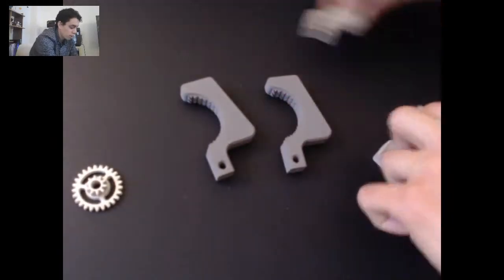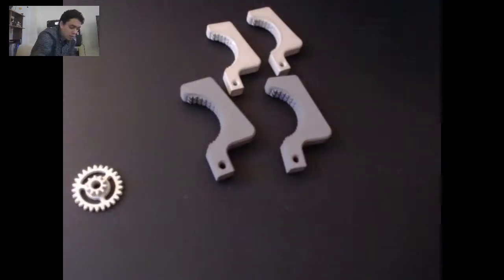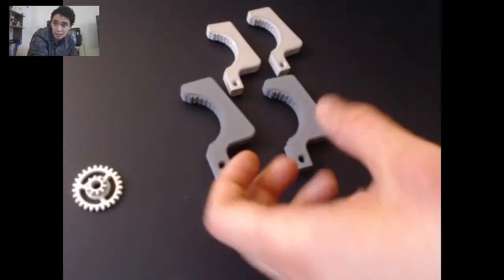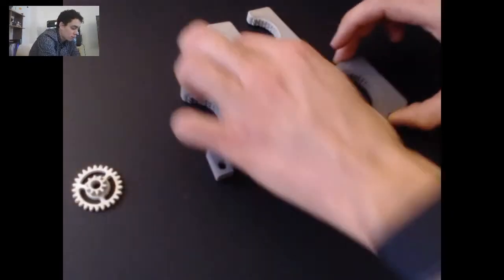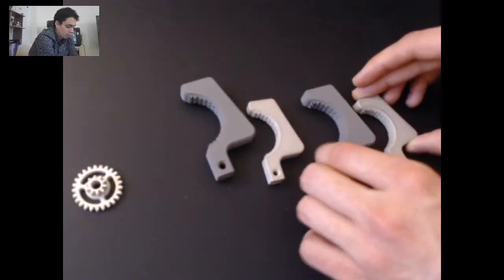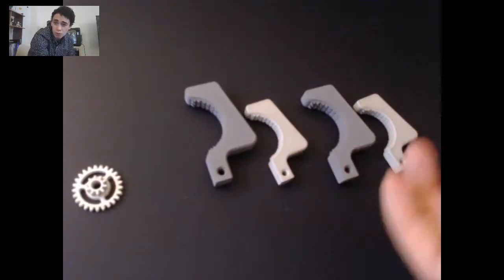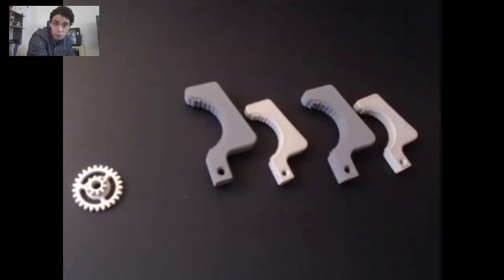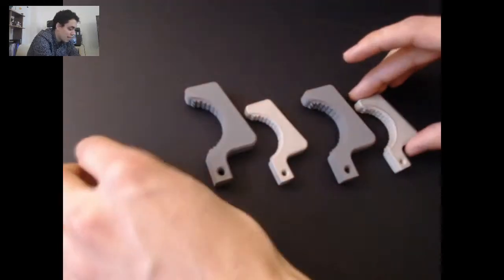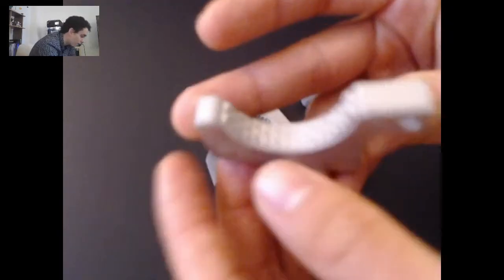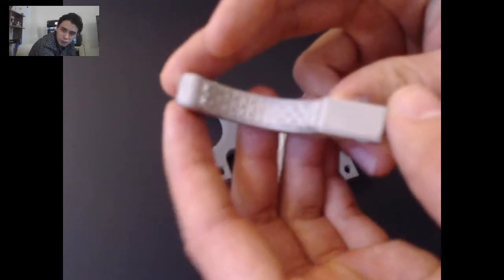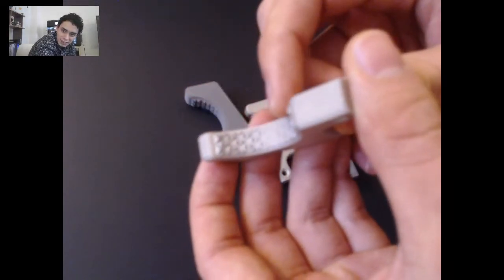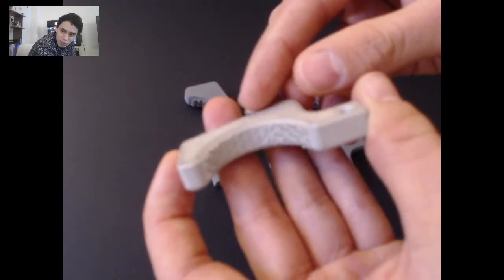This is my green part. These are my sintered parts. As you can see, the shrinkage factor is quite extreme here, as much as 20%, a little bit over 20%. It changes depending on the axis, right? Your parts will shrink more on the z-axis versus the x and y. 20% on x and y, about 26% on the z-axis. The actual quality, the resolution that you get, the ability to print details, the level of detail that you get, is really impressive nonetheless.